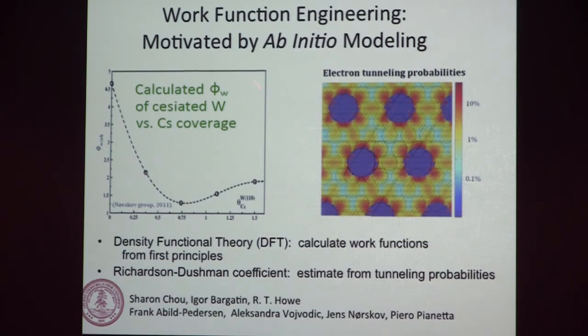So the benchmark is cesium. Cesiated tungsten is what's known and very well studied. And this is a prediction of the coverage, and this is about a 3/4 monolayer coverage, and the effect on work function. You can see it's dramatic on tungsten, and it gets down to around 1.3 eV or something like that. Cesium is not an easy element to deal with, and we would love to dispense with it and work on another approach.